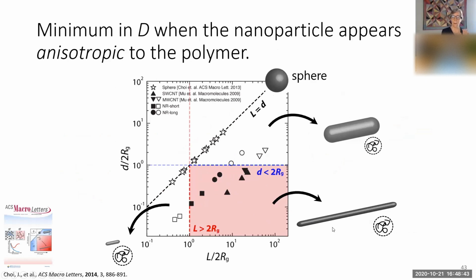And it's very hand waving, and if you think about it too deeply, it's flawed. But somehow the diffusion coefficient perpendicular to the nanorod and along the nanorod are different. And that's where we started thinking about it. It's draining over the nanoparticle and it doesn't know if it's going to go to the left or to the right of the nanoparticle until it's pretty far gone, as opposed to moving along the nanoparticle. I don't think we have a really foundational understanding of that anisotropy of the diffusion coefficient. I don't think we really have a good mechanism.